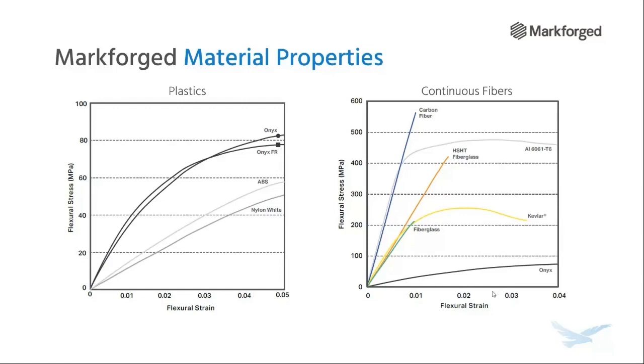Aluminum, again, has a linear curve for a while, then it tapers off after that yield point. And that's where carbon fiber starts to outperform the aluminum. But also look at how much the aluminum will stretch before breakage. And so that carbon fiber has very little movement before breakage. And so you're going to be able to withstand a really high load and then all of a sudden the part will snap under the maximum loading condition. And I'm going to show you a video of a tensile test that shows that in more detail shortly.